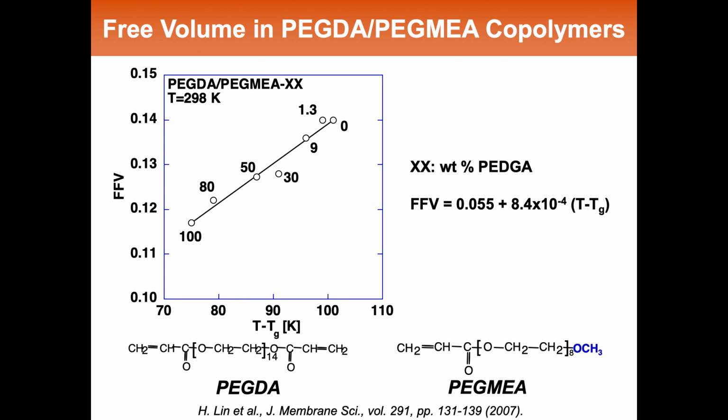And these are materials that are acrylate-based copolymers. Polyethylene glycol diacrylate has 2 acrylate units, one on either end. Polyethylene glycol methyl ether acrylate has 1 acrylate unit. This would form a linear polymer if you polymerized it through these acrylate units. This is the cross-linker. And if you make mixtures of these two, then you polymerize them, you get a cross-link network with these methyl ether acrylate dangling ends in that network.